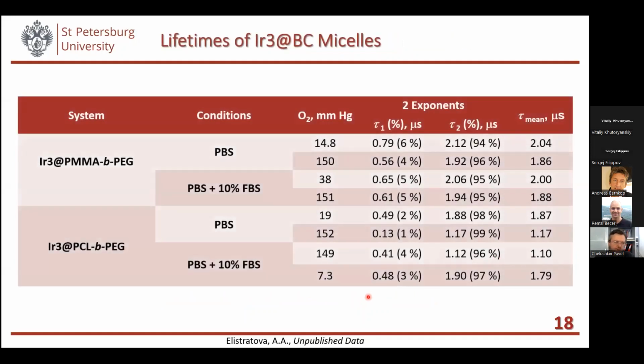And the same situation was for the third block copolymer micelle based on PMMA. So it looks like PMMA is too rigid a matrix for the complexes, and in this case, oxygen does not reach the phosphors and doesn't quench their luminescence.